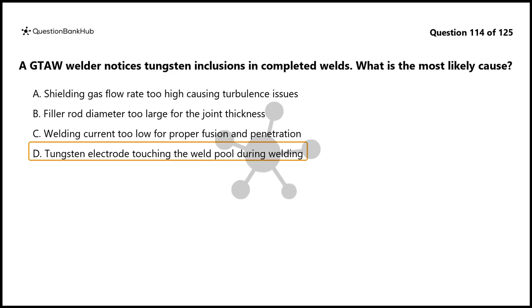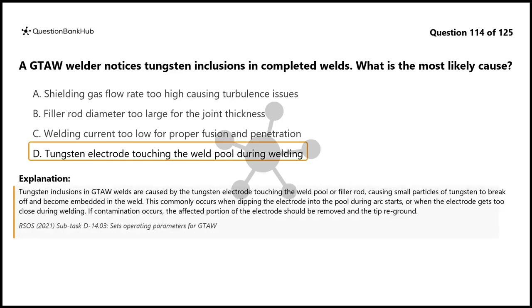The correct answer is D. Tungsten electrode touching the weld pool during welding. Tungsten inclusions in GTAW welds are caused by the tungsten electrode touching the weld pool or filler rod, causing small particles of tungsten to break off and become embedded in the weld.